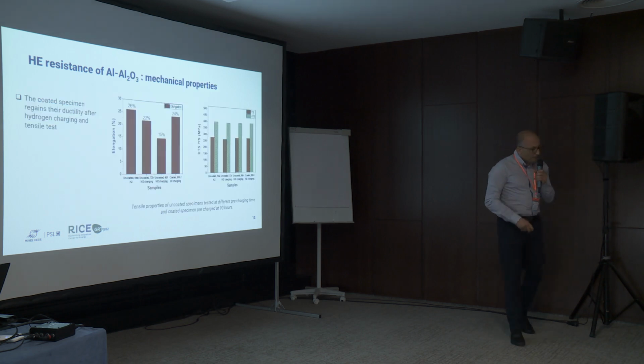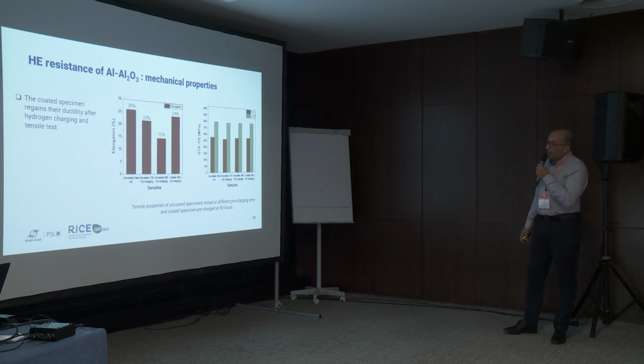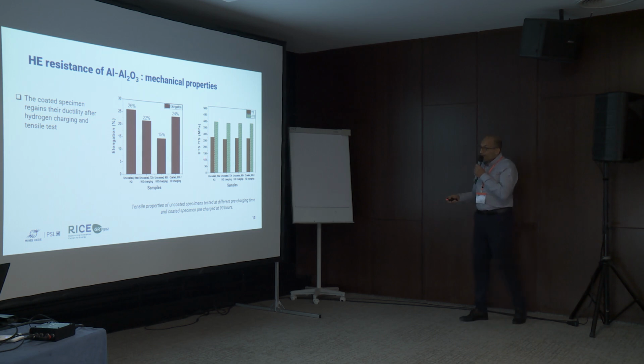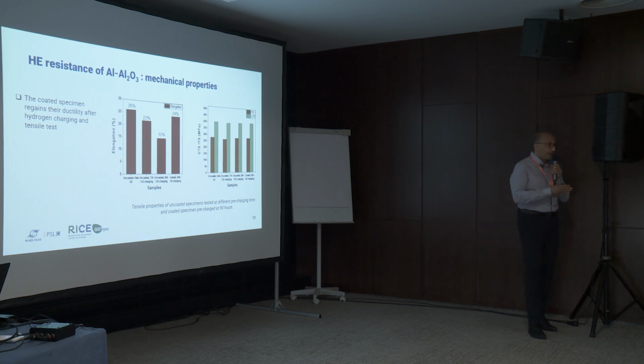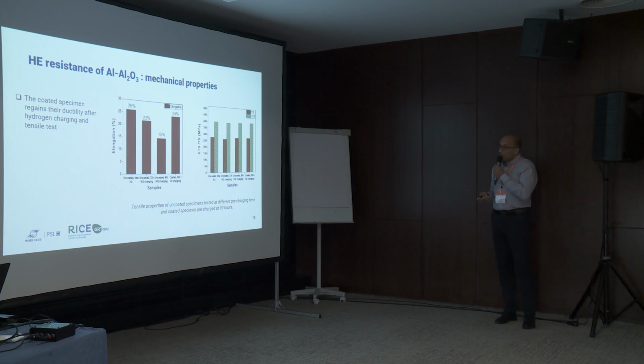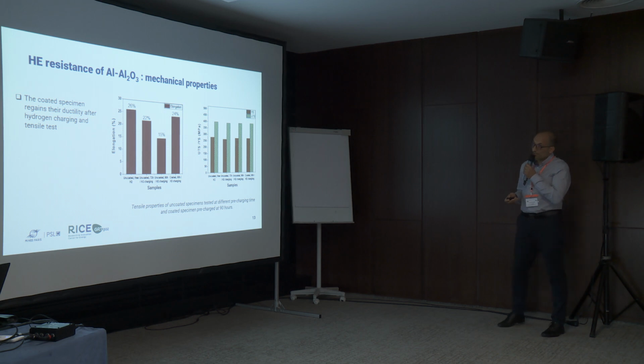So, the effect of hydrogen embrittlement on the mechanical properties. On the right side, you see no effect on the tensile strength. UTS and yield strength are not affected by the hydrogen charging condition, whereas the ductility is affected, and we have an effect of the charging time. And we regain the ductility after coating, with the same magnitude as the as-received material.